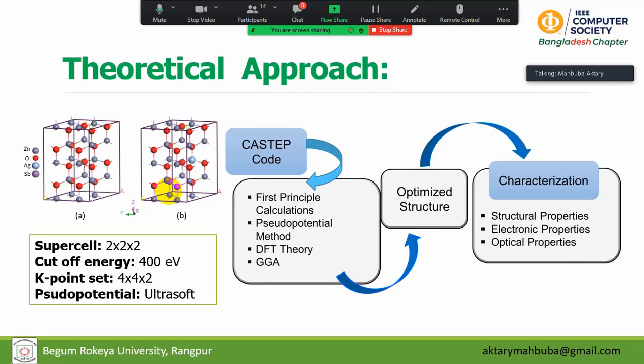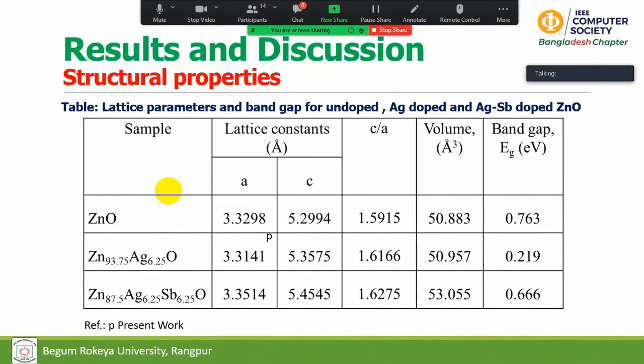And after that, I characterize some structural properties, electronic properties, and optical properties using GGA, actually generalized gradient approximation, I've used to clarify and to get more reliable result for exchange correlation. Here you can see the structural properties of zinc oxide, single doped zinc oxide and dual doped zinc oxide. The lattice parameter in this table, you can see the lattice parameters and band gap for undoped, silver doped and silver antimony doped zinc oxide.